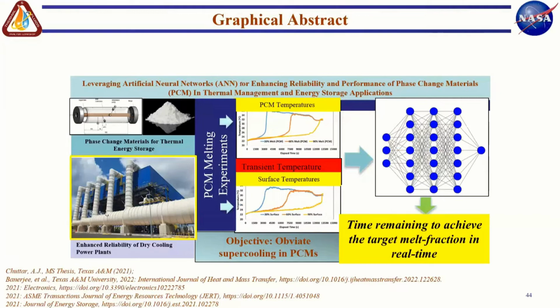So there is a lot of interest in using phase change materials for dry cooling of power plants. But the enigma there is, typically salt hydrates are considered an attractive material, but salt hydrates actually have very poor reliability. In other words, it's very easy to melt them, but it's very difficult to solidify them. You need a substantial amount of subcooling in order to initiate solidification. And so we looked at machine learning algorithms as a way to predict when you are going to hit a particular melt fraction.